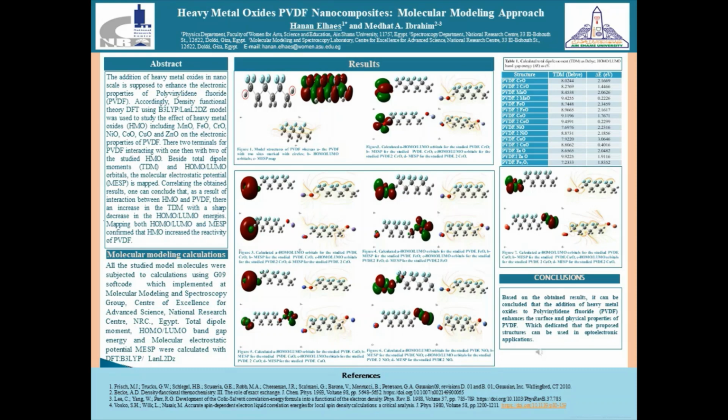Besides total dipole moments and HOMO-LUMO orbitals, the molecular electrostatic potential is mapped. Correlating the obtained results, one can conclude that, as a result of interaction between heavy metal oxides and polyvinylidene fluoride, there is an increase in the total dipole moment with a sharp decrease in the HOMO-LUMO energies. Mapping both HOMO, LUMO and molecular electrostatic potential confirmed that heavy metal oxides increased the reactivity of polyvinylidene fluoride.